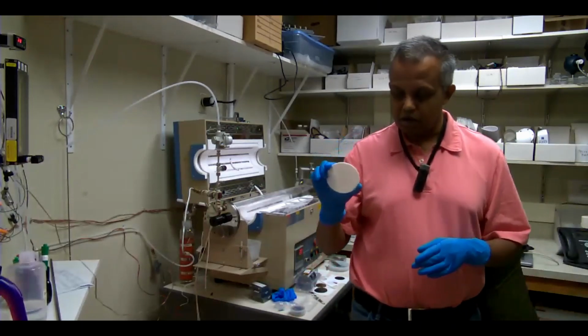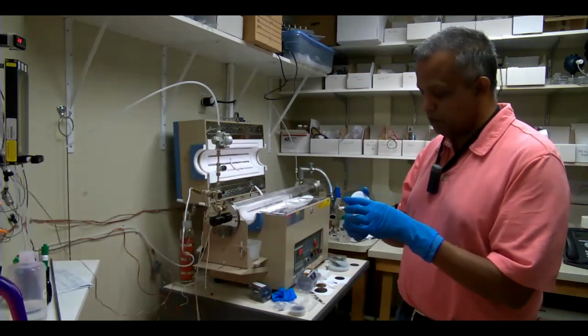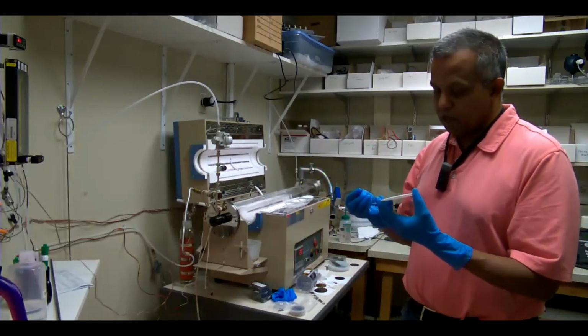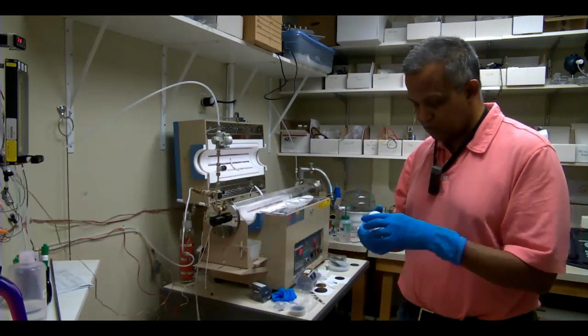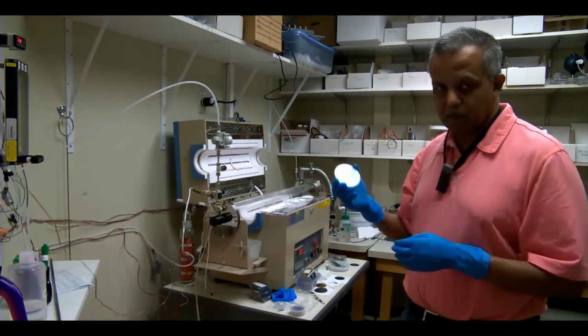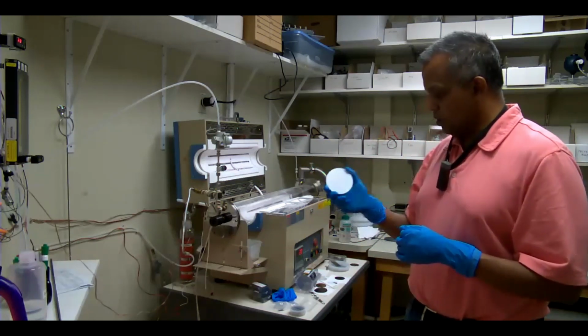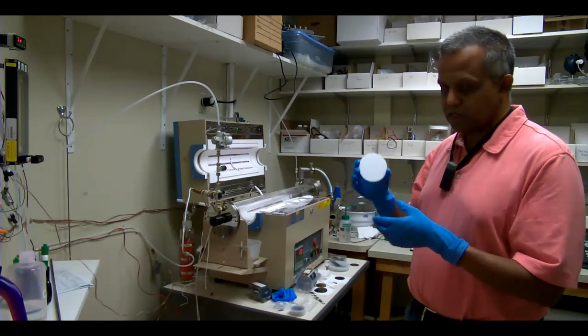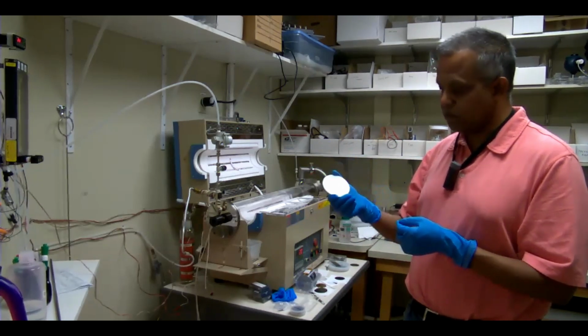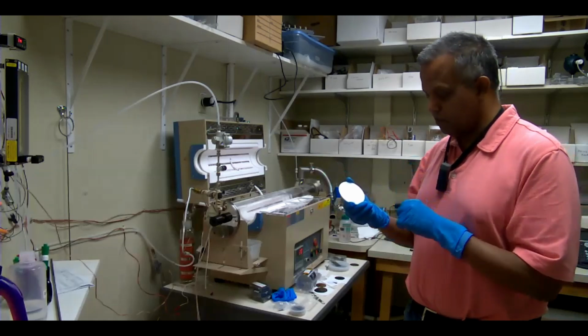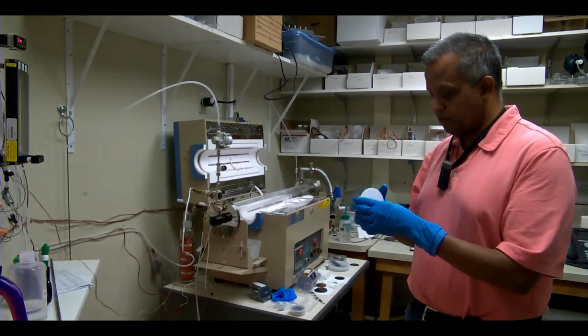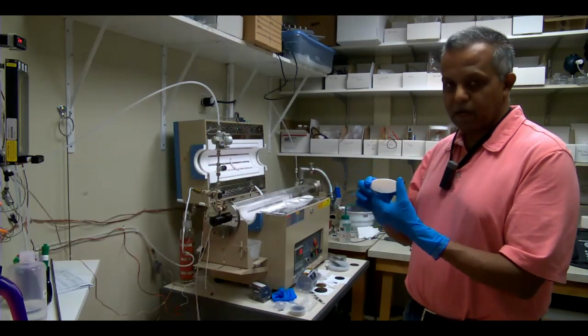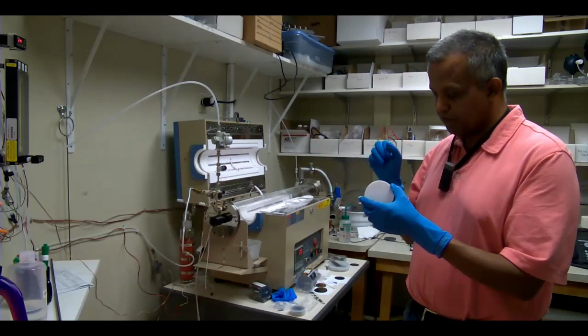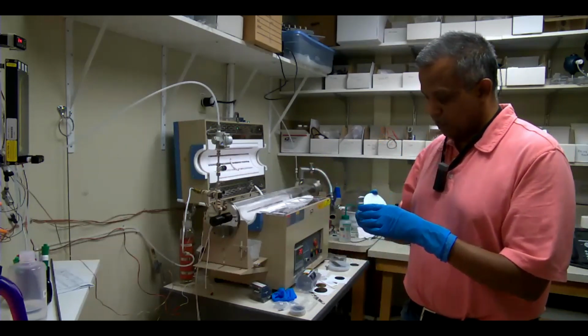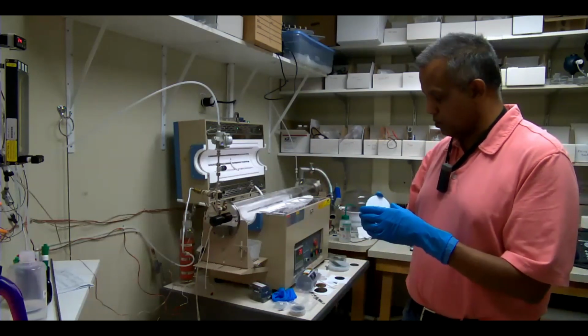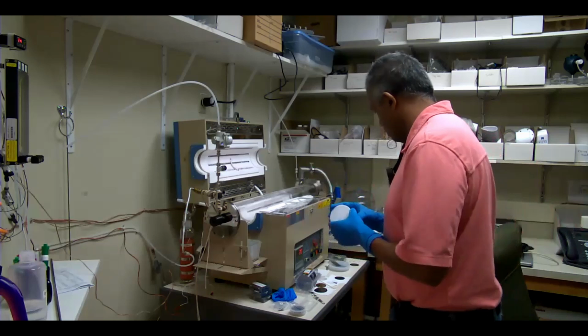So this is the boron source, boron oxide, but it's not straight boron oxide because boron oxide melts at 500 Celsius or somewhere around there. So we're going to be running it today at 1100. This is actually a glass, a ceramic that consists of aluminum oxide, magnesium oxide, and embedded inside is some boron oxide. So basically, when it gets hot, the boron oxide embedded in this disc will start coming out, vaporizing and depositing on the surface to produce our dopant source, which gets driven into the silicon.